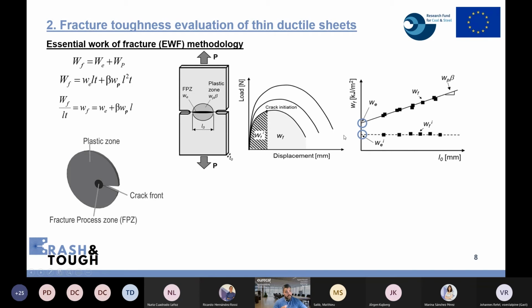By means of simple mathematical and statistical analysis, you obtain this specific essential work of fracture, which represents the crack propagation resistance of the material, and in certain materials it could be related to the elastic-plastic fracture mechanics value, the JC.